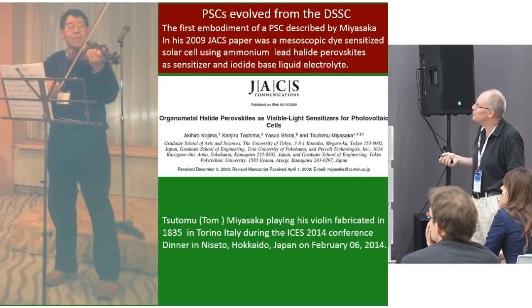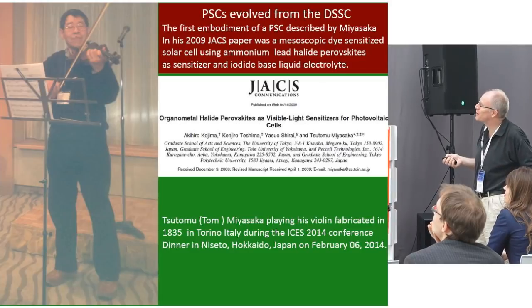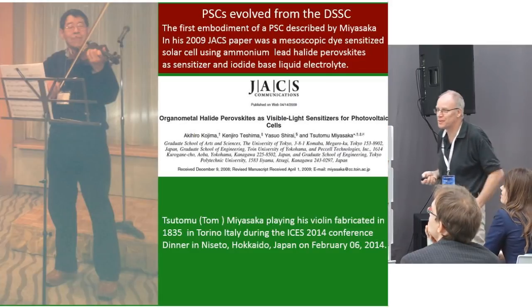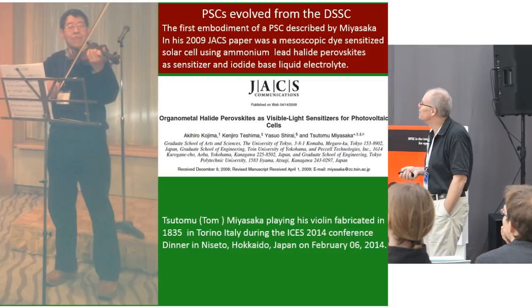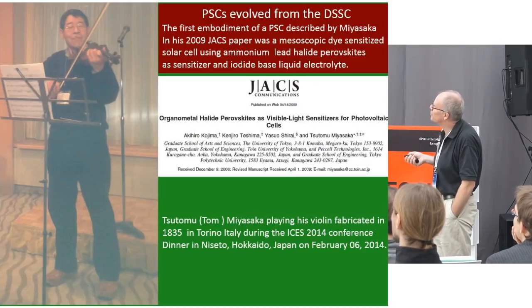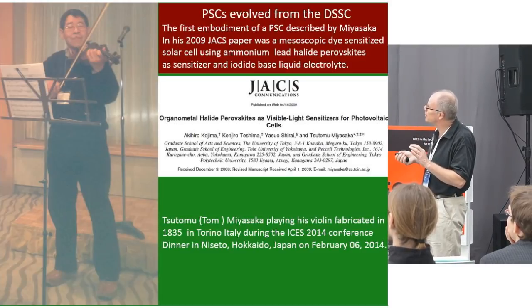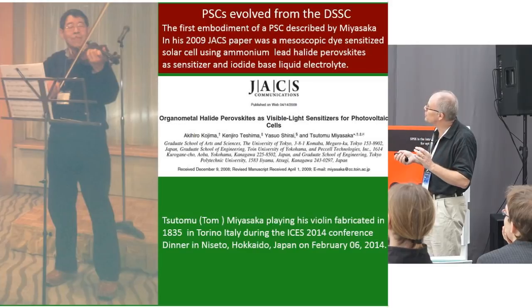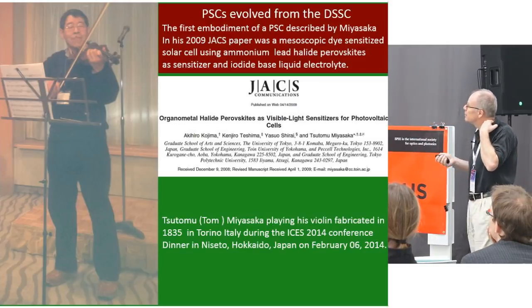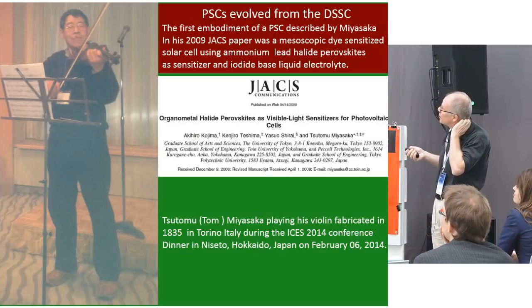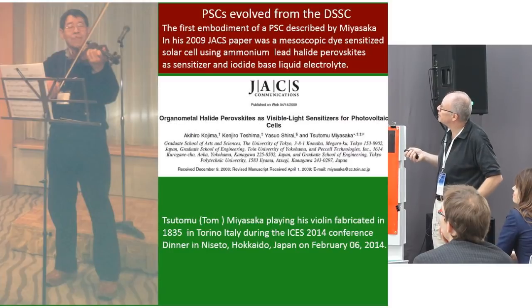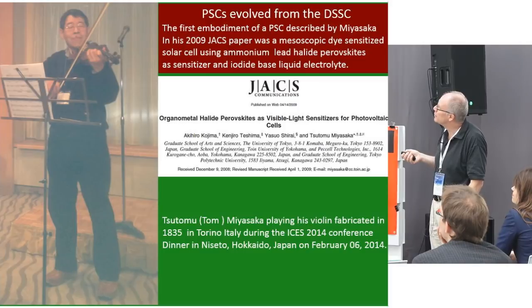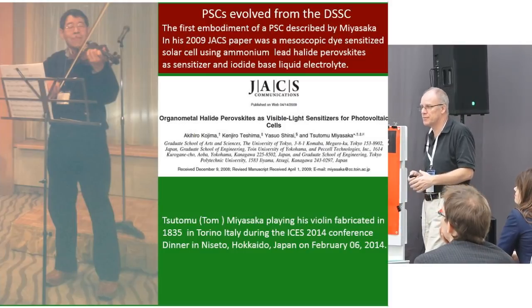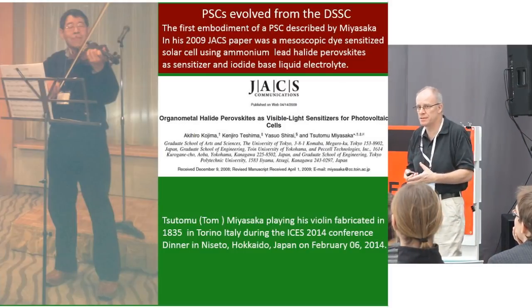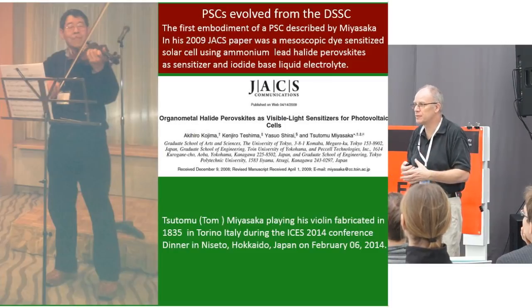But when we discuss what you do besides being a scientist, this is one example of what you can do as a hobby. He published and started to work on sensitizing TiO2 with a perovskite material. It's a methylammonium, that's an organic ion, lead triiodide. That was the starting point. And it was basically not very successful. He could measure 3% efficiency, so not very extraordinary.